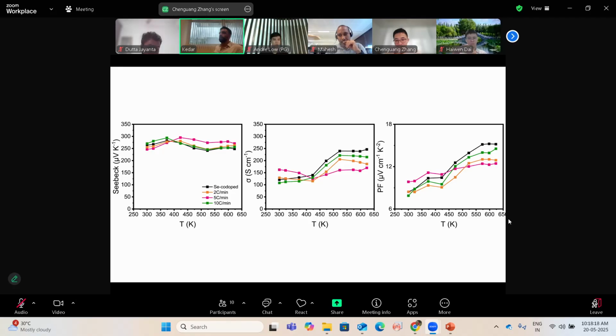I think you should still measure the thermal conductivity. You have samples left for thermal conductivity, right? Actually, for the thermal conductivity, only the post-annealing sample and the 10 Celsius per minute sample can be measured, because for the 2 Celsius per minute and the 5 Celsius per minute, it created more cracking inside the sample. It's very hard to cut an LFA sample. But that's okay.